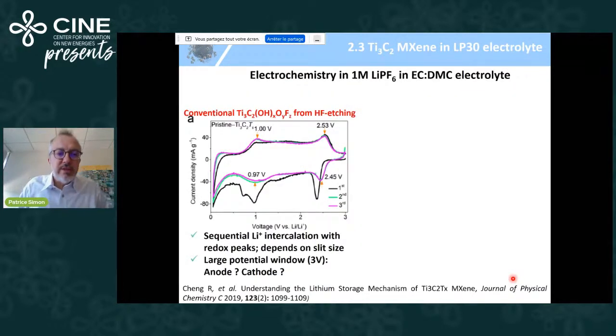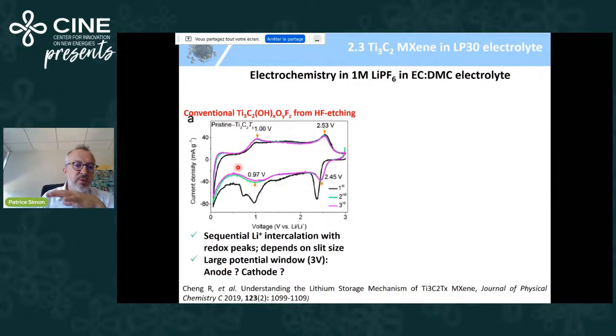And here I'm going to show you the electrochemistry in LiPF6 EC-DMC electrolyte, which is a lithium-ion battery electrolyte, the electrochemical characterization of MXene prepared from HF, containing fluorine groups. You see that this is a very blurred electrochemical signature. You have few redox peaks, and the lithium intercalation proceeds within 3 volts. So it's not a good anode, it's not a good cathode, because the operating voltage is too high. And you have a sequential lithium intercalation with several redox peaks again, but really not nice or interesting. Obviously, if you integrate the capacity over this whole potential range, you can reach high numbers, up to 200 milliampere hour per gram, but this does not make sense because the potential window is too large.